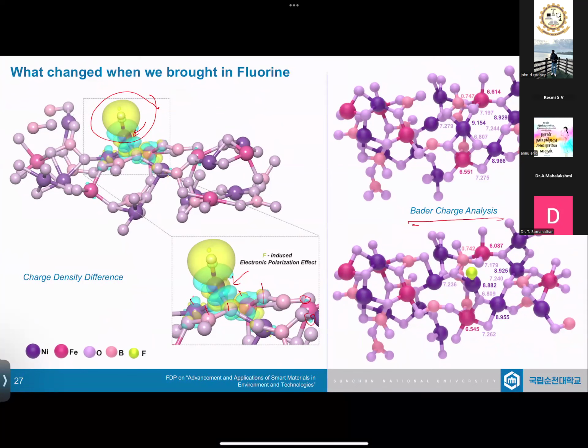To confirm, we did the Bader charge analysis, where we tried to measure the charge of each atom in a normal system and also in a fluorine system. We found out that the charge of every atom surrounding it is at least being altered in a very slight manner, which confirmed our theory.